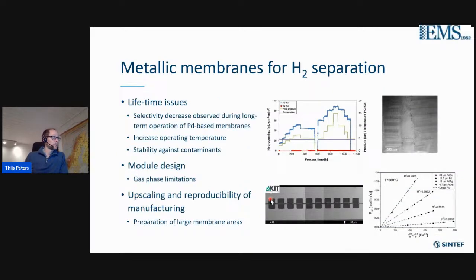Most of the issues related to metallic membranes are related to lifetime. It's a high temperature membrane process, so you have to make sure that the membrane behaves in a stable manner for a long time at these temperatures of interest, so up to 600 degrees. And then normally what we see is a selectivity decrease, especially at the higher operating temperatures, and also the stability against contaminants is an issue.